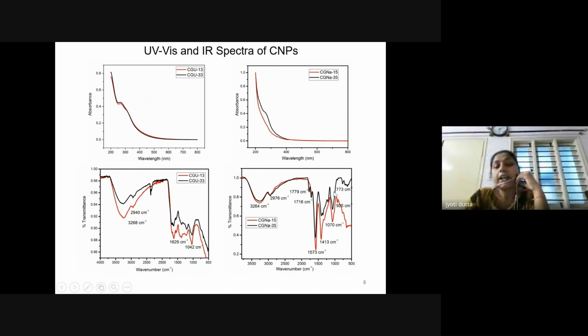The stretching and bending vibrations of the C-H bond are also observed at 773 centimeter inverse and 925 centimeter inverse. So we can understand that these carbonaceous nanoparticles contain multiple functional groups on their surface and probably in the bulk, because if we look into the elemental composition, the oxygen content is quite high for these carbonaceous nanoparticles.